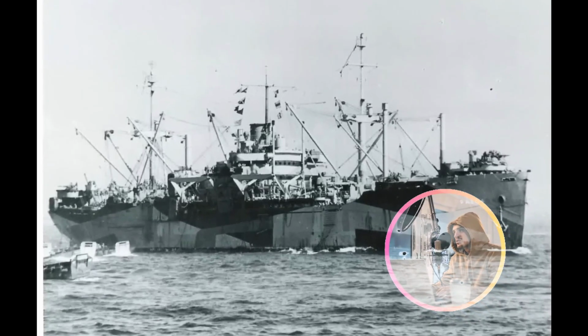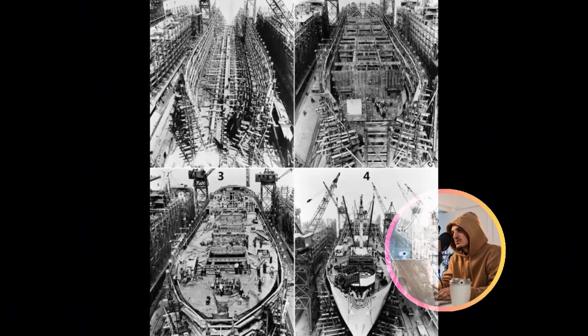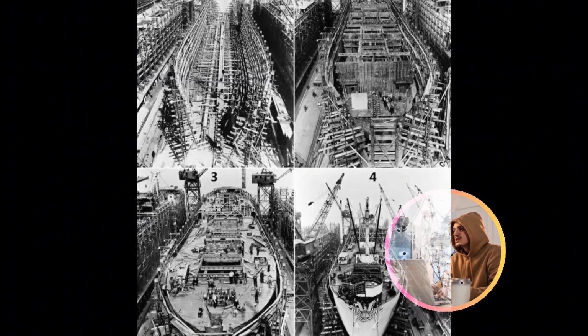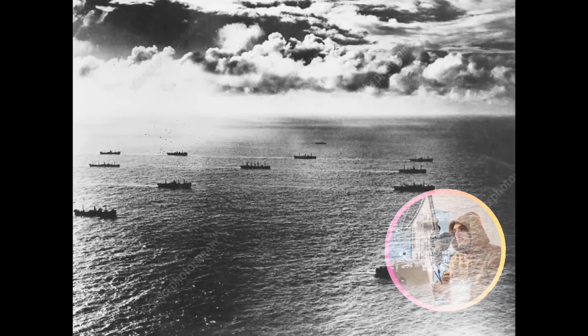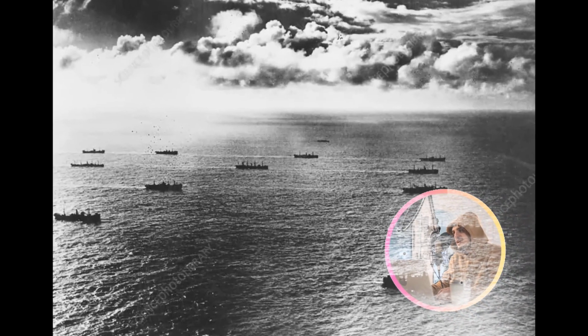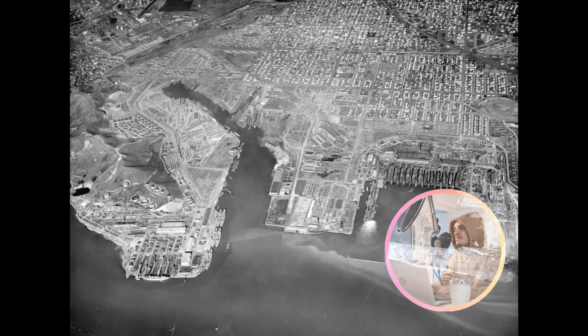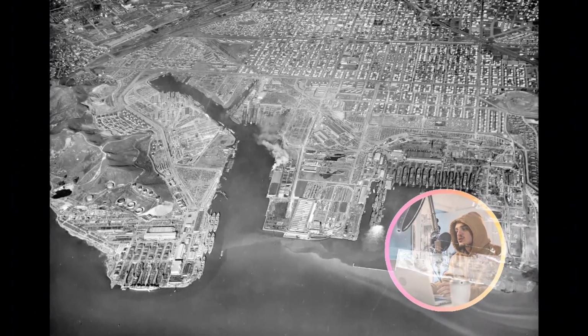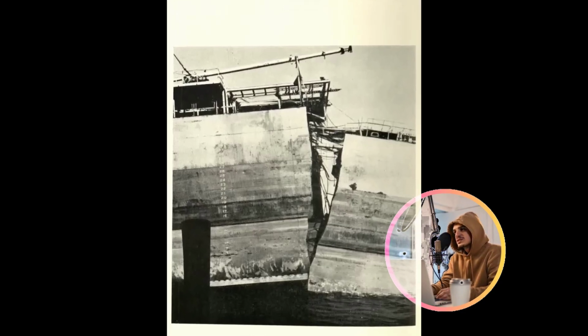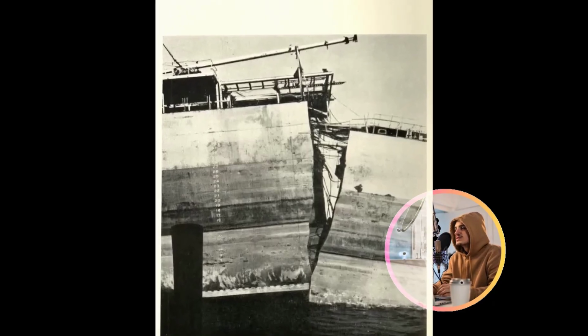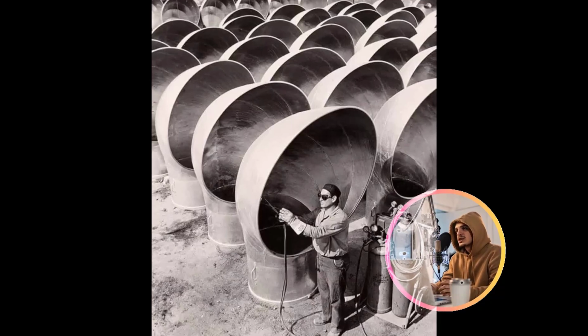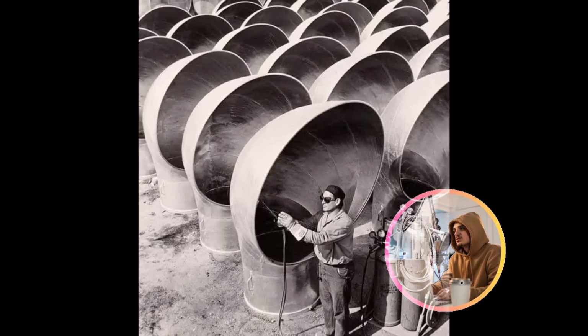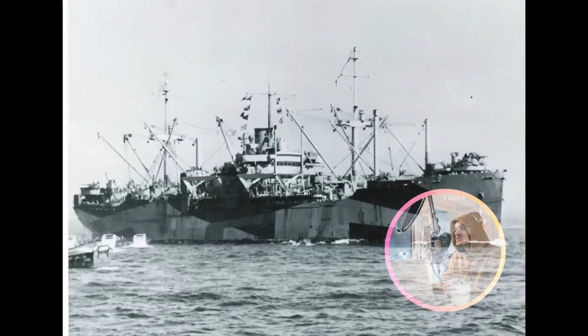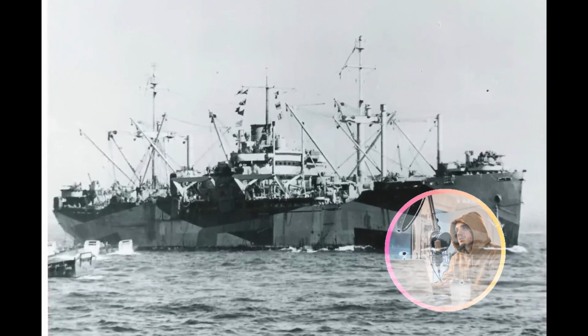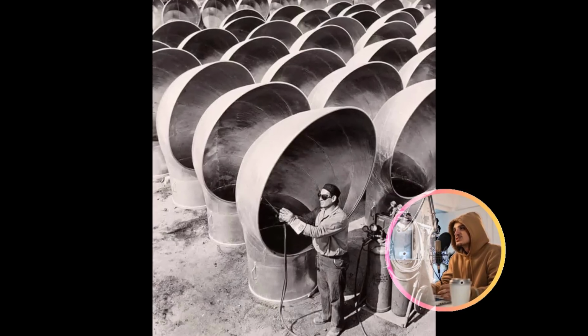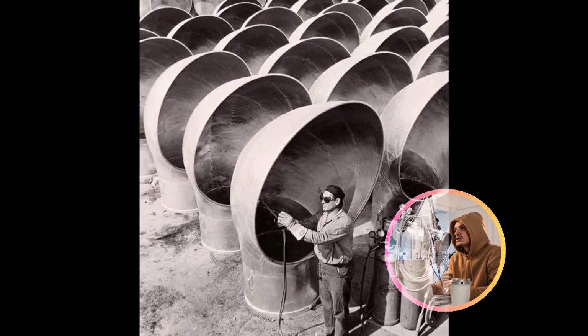Traditional vessels, constructed using rivets, were notably immune to this specific type of failure, and understanding this distinction profoundly elucidated why welding techniques had, for a time, appeared to carry a peculiar curse. Riveted construction is, by its very nature, fundamentally segmented. Each individual riveted plate functions as a distinct, separate element within the overall structure. Cracks that might initiate within one panel invariably encounter a riveted seam and are effectively arrested there. The overlapping plates and the numerous mechanical fasteners collectively create inherent, natural barriers to crack propagation. In stark contrast, welded ships are seamless, continuous structures. A crack originating in a single plate can thus traverse unimpeded through hundreds of feet of uninterrupted welded seams.